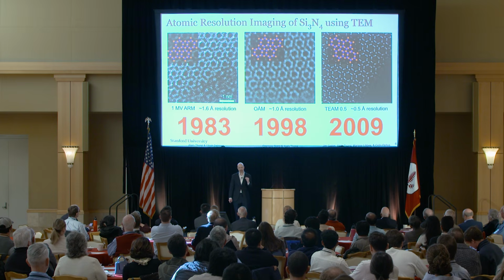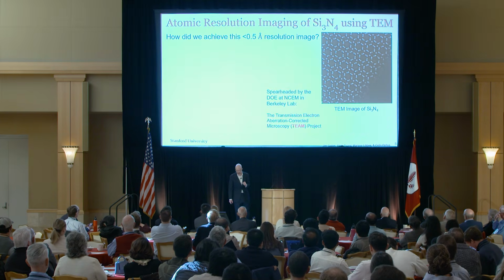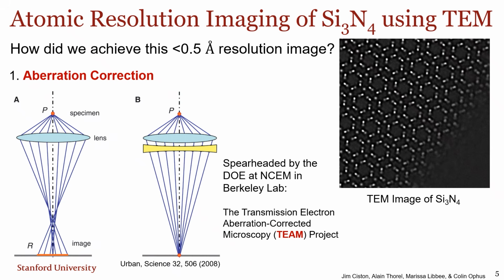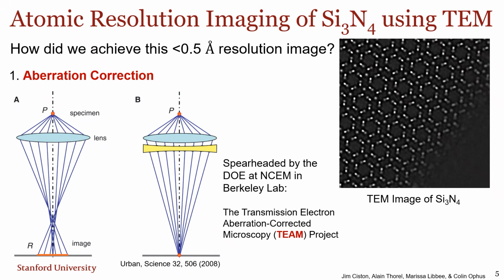So I want to quickly explain how we were able to achieve that image. The first technology that my group also works on is aberration correction. I'm wearing glasses. They can parabolically focus light down to a point, but unfortunately electron lenses have this intrinsic blurring. It's called spherical aberration, and it was responsible, for example, for those blurry images in the Hubble Space Telescope. We had to send a NASA mission up into orbit to install an aberration corrector, and believe it or not, the optics required to do aberration correction in TEM is even more complex. We've gone from 6 or 9 lenses in the microscope to hundreds of lenses.